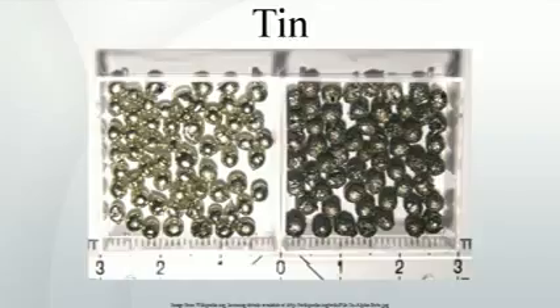The problem was partially solved by Sony. A tin intermetallic compound with cobalt, mixed with carbon, has been implemented by Sony in its Nexelion cells released in the late 2000s. The composition of the active materials is close to Sn0.3Co0.4C0.3.